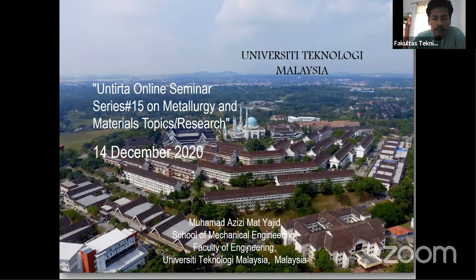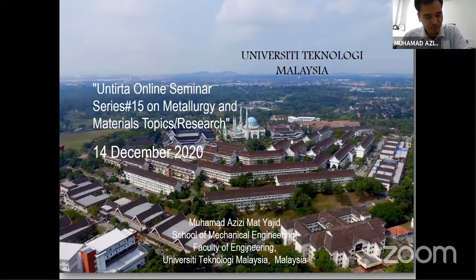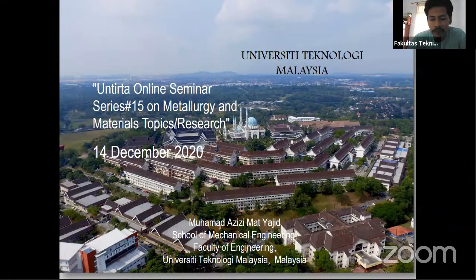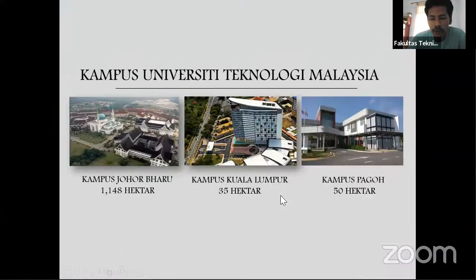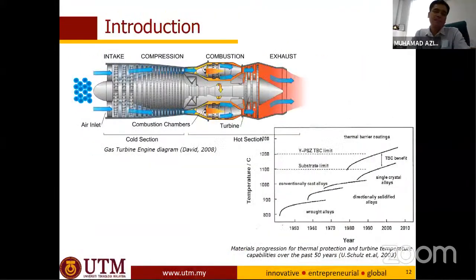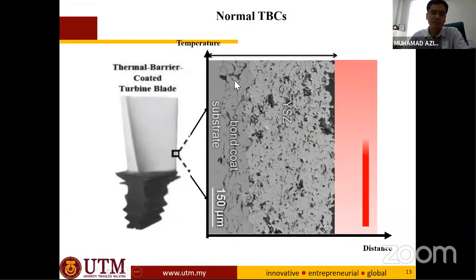As you said, between the substrate and the thermal barrier coating, we need a bond coat. Yes, exactly. Can you explain to us what considerations we must take into account to choose this bond coat material? Yes. The bond coat, as I say, is very crucial, because it is like an intermediate layer. You have the substrate here, which is a metal, for example nickel alloys, and then you have the ceramic. The coefficient of thermal expansion of the ceramic and the metal is very much different.